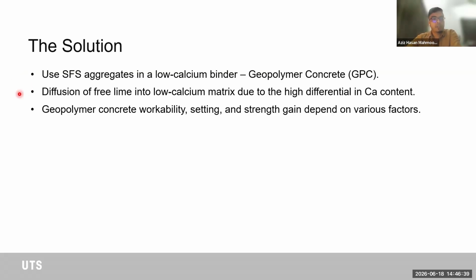Now, this was chosen to allow for the diffusion of free lime into the low calcium matrix due to the high differential in calcium content between the aggregate and the cement paste, or the geopolymer paste that we have here. The other challenging aspect of geopolymer concrete is the workability. The property can range from very short setting time to very high setting time, depending on how you design the concrete. And also, the setting time can be a little challenging if you do not have your proportions right.